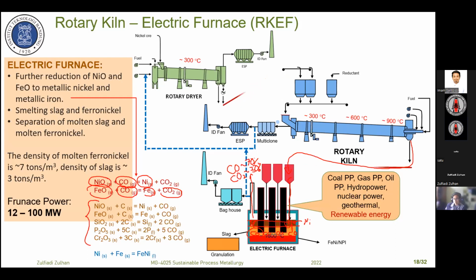The main reactions actually occur during the heating up of the calcine, and also some reactions occur in this area. In that area, nickel oxide is reduced by carbon. Also in the calcine, the reaction takes place, and iron oxide is reduced by carbon to produce nickel and iron.